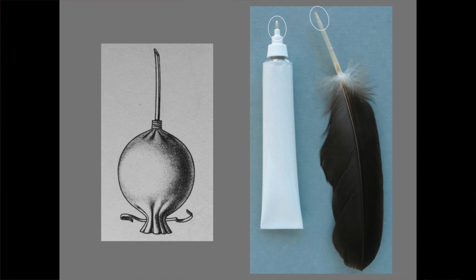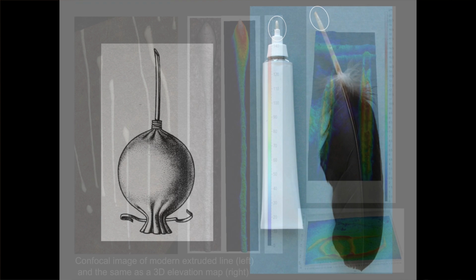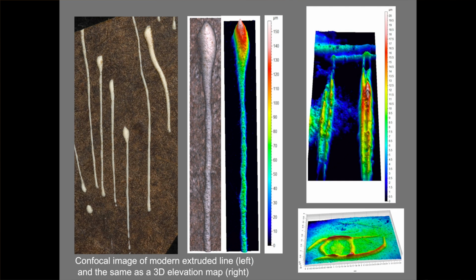Instead of an animal bladder, I constructed a tube with a goose feather quill tip and filled it with a slightly dilute commercial spackling compound, which I extruded onto a surface. This method could indeed produce very thin lines, but they had a smooth surface and not the furrowed or ridged profile of the ancient lines. Also, a blob of medium formed at the beginning of each line, which could not be observed on the ancient lines. This confirmed that the relief lines were definitely not extruded.